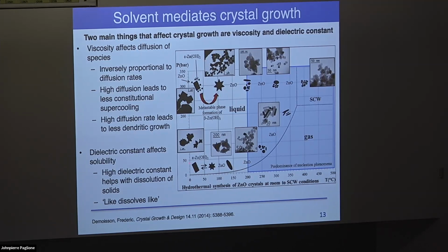So this is just a plot of zinc oxide crystals being formed hydrothermally at different temperatures and different pressures. The pressure got cut off there. Oh no, it's up here, sorry. You can see that you have different structures or morphologies being formed in different regimes, and that's all because water has a different dielectric constant and different viscosity at those different temperatures. This is just a quick pointer about tuning, something you would most likely get into later on down the line. Optimizing the crystal growth is actually optimizing the viscosity or the dielectric constant of your solvent to make sure that you are growing optimal crystals for your system.